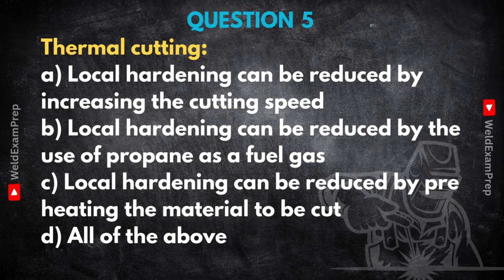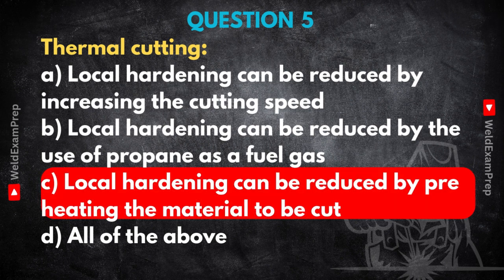Okay, so how do we avoid that? The most effective way listed here is C. Preheating the material to be cut. Preheating, how does that help? Well, if you raise the overall starting temperature of the material before you cut it, then after the cutting flame passes, the cooling rate of that HAZ is significantly slower. Ah, because the surrounding metal is already warm. Exactly. The temperature gradient isn't as steep.